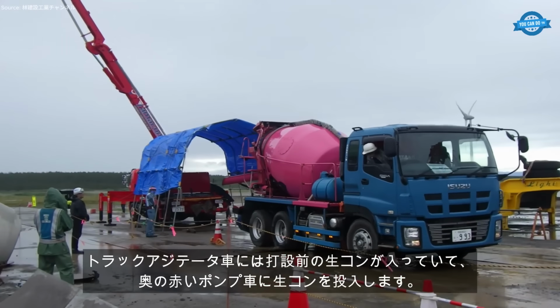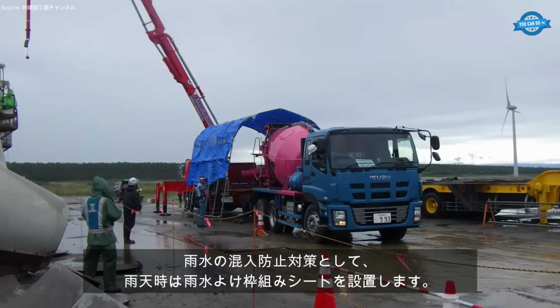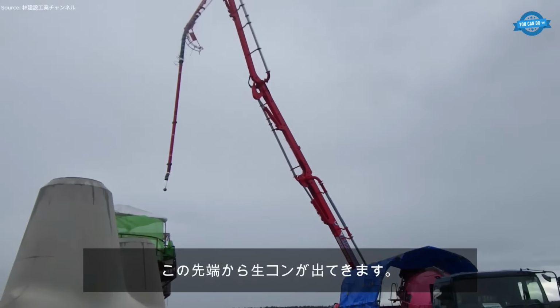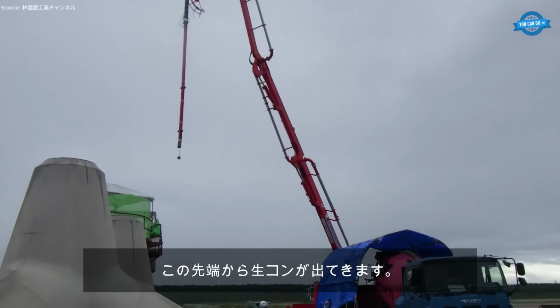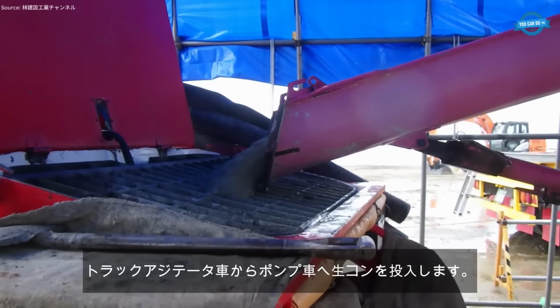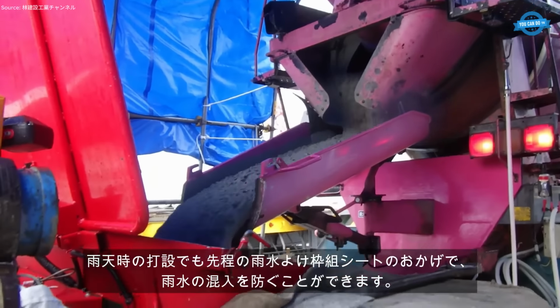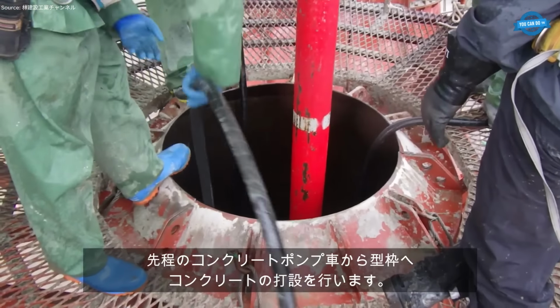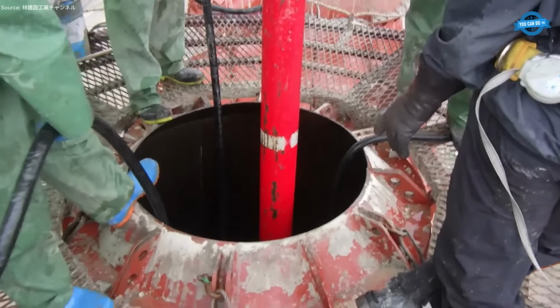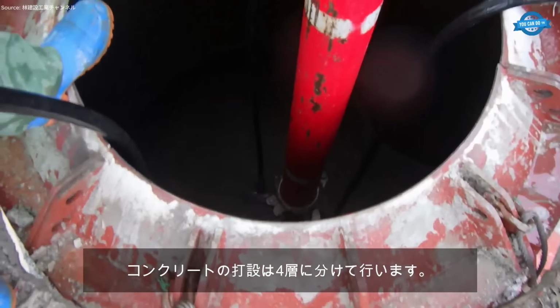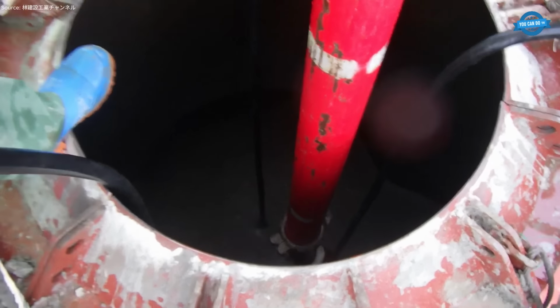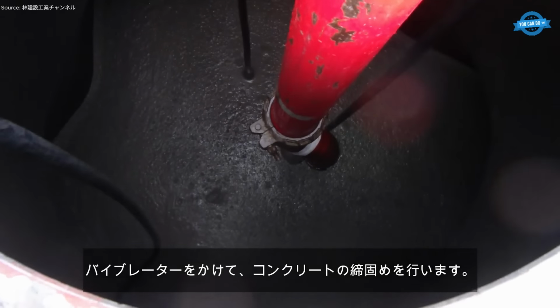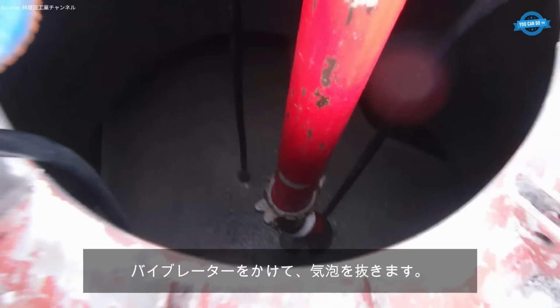Concrete arrives in agitator trucks, then is transferred to the red pumping vehicle, which delivers the mix directly into the mold. In rainy conditions, protective frame-mounted covers prevent rainwater contamination. Before pouring, on-site tests are conducted, including slump, air content, temperature, and unit water measurement. Sample test pieces are also cast for later compressive strength verification. Placement is carried out in 4 successive layers.